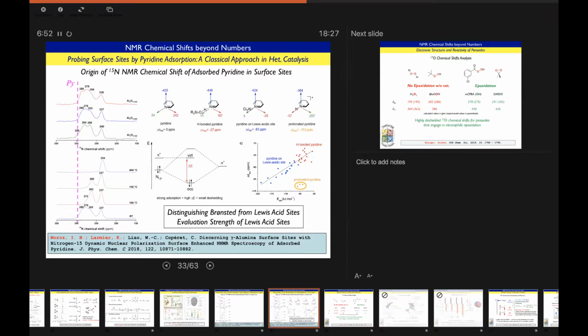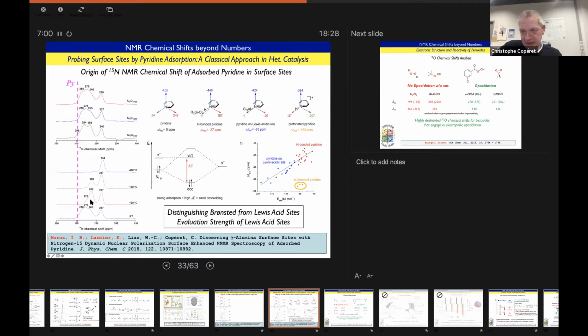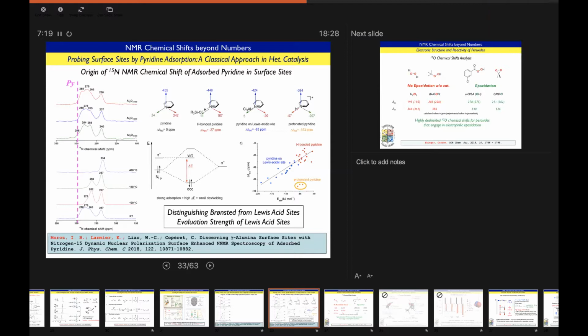I see. DNP is usually done at 100 K, and here it seems to be a static experiment. Yes, this is 100 K as well, because in the case of pyridine, pyridine hops from site to site. If you do that at room temperature, you get an average, a chemical exchange, and the information you get is lost. So you actually work in a frozen state anyway, and you use DNP to enhance your signal. I see. Okay. Yeah, thank you.